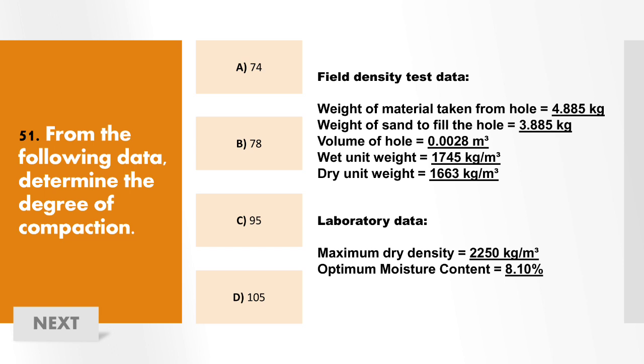So given field density test data, weight of material taken from the hole is equal to 4.885 kg. Weight of sand to fill the hole is equal to 3.885 kg. Volume of hole is equal to 0.0028 cubic meter. Wet unit weight is equal to 1,745 kg per cubic meter. Dry unit weight is equal to 1,663 kg per cubic meter. Laboratory data, maximum dry density is equal to 2,250 kg per cubic meter. Optimum moisture content is equal to 8.10%. So para makuha ang degree of compaction, equal siya sa dry unit weight over maximum dry density. So bali 1,663 over 2,250 times 100 is equal to 74% or letter A, 74.